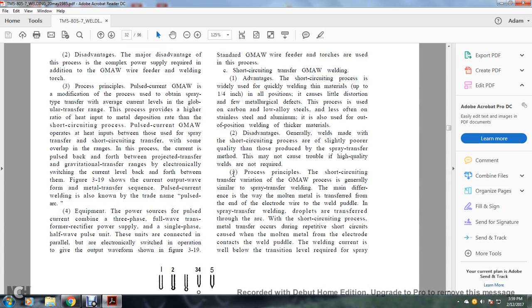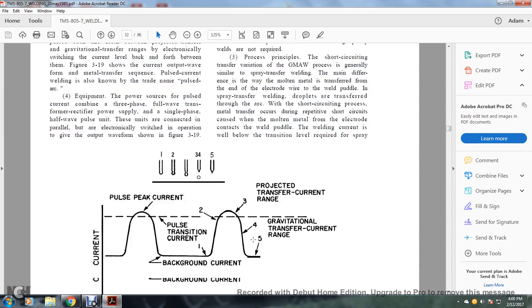Process principle: short-circuiting transfer is a variation of the gas metal arc welding process and is generally similar to spray transfer welding. The main difference is in the way the molten metal is transferred from the end of the electrode wire to the welded puddle. In spray transfer welding, droplets are transferred through the arc. With the short-circuiting process, metal transfer occurs during repetitive short circuits caused when the molten metal on the electrode contacts the welded puddle. The welding current is well below the transition level required for spray.